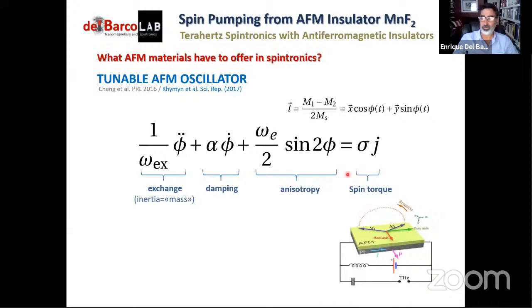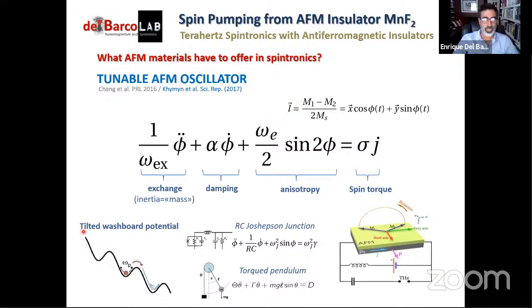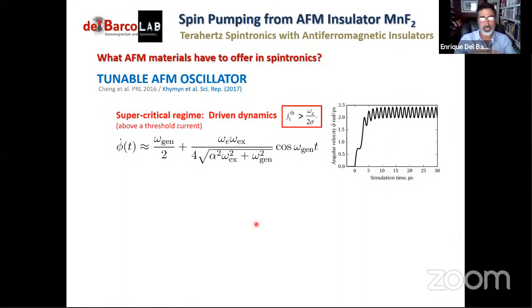Well, actually, this equation is very common in physics. It's known as the tilted washboard potential, and it describes many systems, like, for example, RC-shunted Josephson junctions, or a classical torque pendulum, where we have local minima for the system to be in, and then there's some inertia, so that if we push the system, it will start going down the ladder. Okay, so if we analyze the results, we find that we have two regimes, and the two regimes are separated by a threshold current. That threshold current depends on the anisotropy of the antiferromagnet and sigma, that is basically the efficiency in converting charge current into a spin current, or the spin Hall angle, if you want.